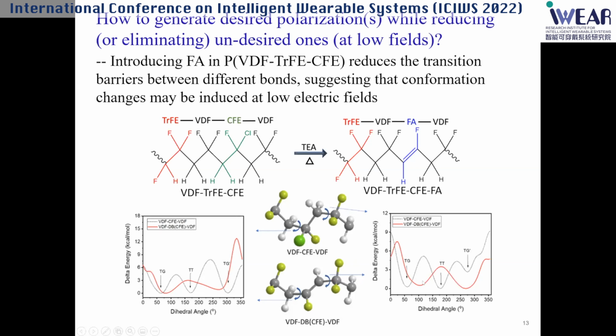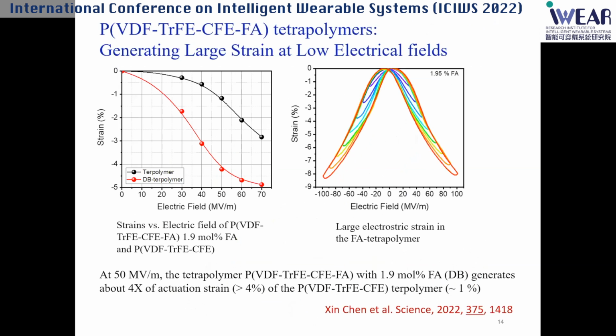This really suggests this approach could be very attractive, and this means we need to convert the polymer from the terpolymer to the tetrapolymer. Once we think about this, it's really not so hard. Basically what you see is, if we convert about 2% more of CFE into the double bond, we can generate strain - for example at 50 megavolts per meter, we can generate strain about 4 times higher than the terpolymer. This is very surprising.